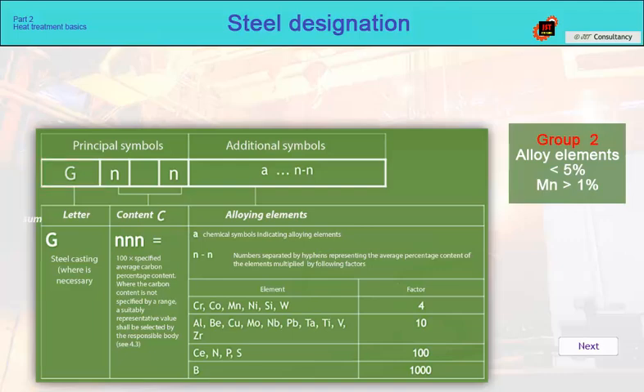For these steels, individual alloying elements are listed, expressed by a number according to the table. The main alloys, chromium, cobalt, manganese, nickel, silicon or tungsten, are multiplied by a coefficient of 4, the other elements by 10, the others by 100, and the content of the element boron by 1000. The alloying elements are listed in the order in which they appear in the table. For example, chrome vanadium steel